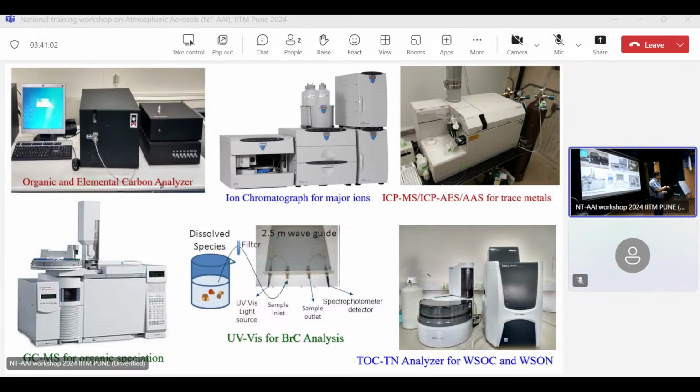In case of ICP-AES, you put everything in plasma. The first class he was talking about plasma. You put things in plasma, everything gets ionized. And then things come back and they emit different wavelengths. So it is emission spectroscopy. Whatever wavelengths it is emitting, you measure them, calibrate them, and get the result.